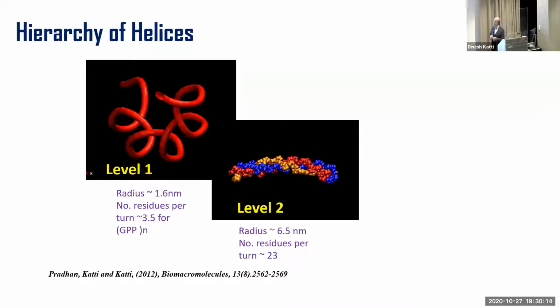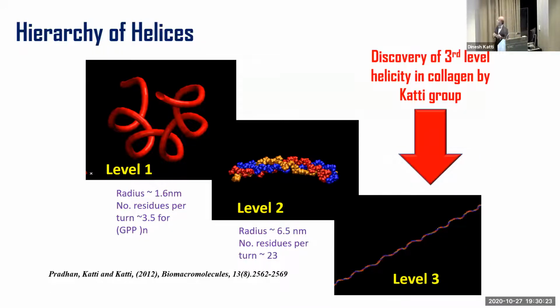And so what we did was to run simulations for the full length 300 nanometer long collagen. And so we did that. And what we discovered was that there was a third level of helicity in the collagen. So basically, this triple helix twists at a pitch of 15 nanometers. So not only do we have this triple helix, but the triple helix itself twists in a right-hand helical manner. And so that was a major discovery coming out of our group on the collagen. But then, like every engineer, so what's the point? I mean, what does that mean?